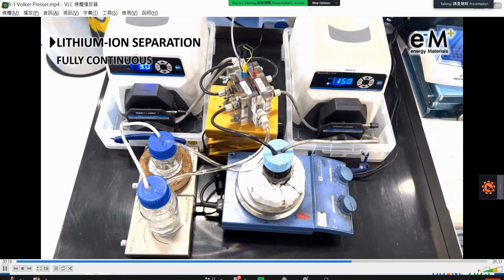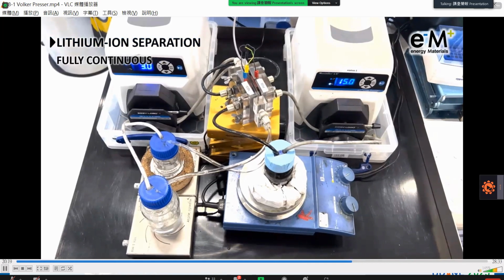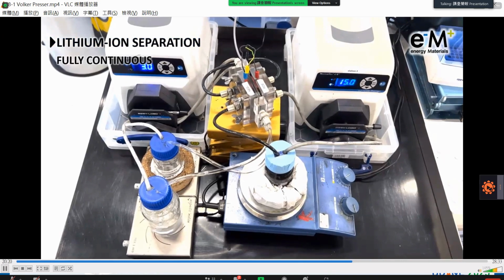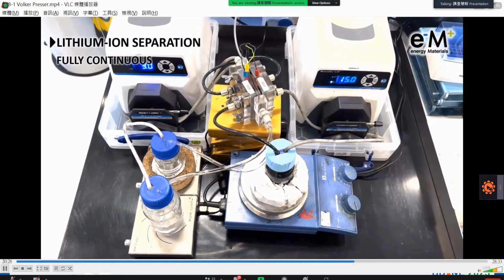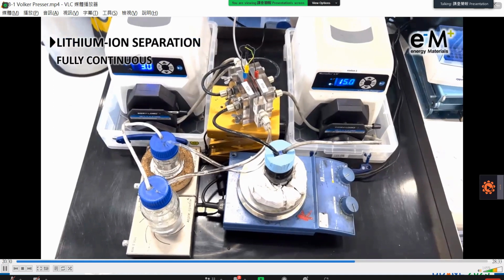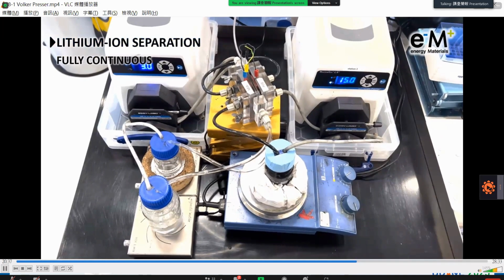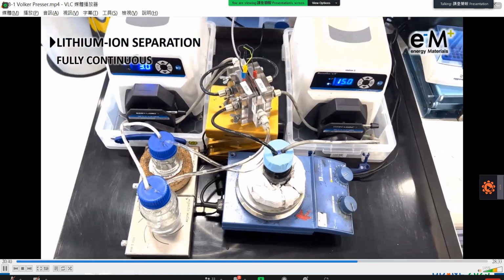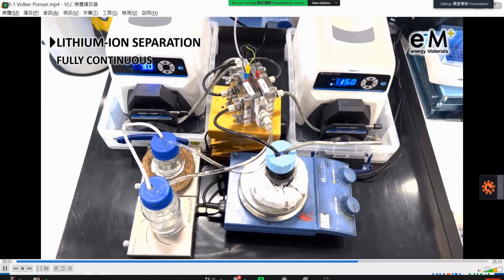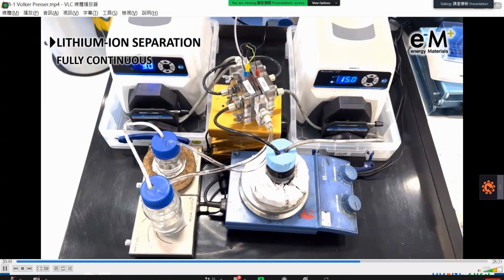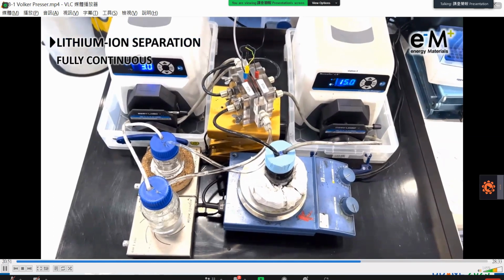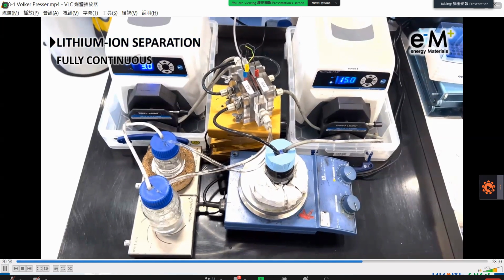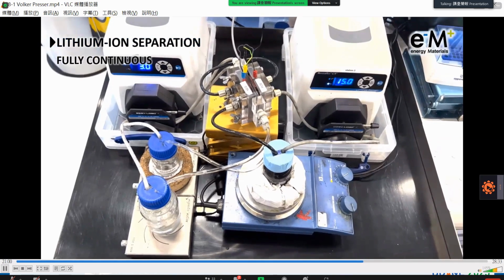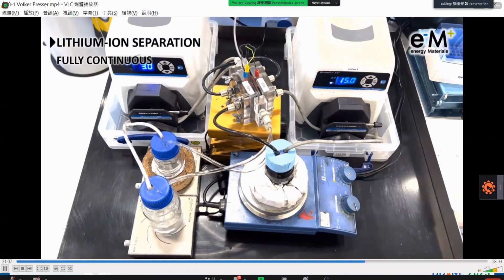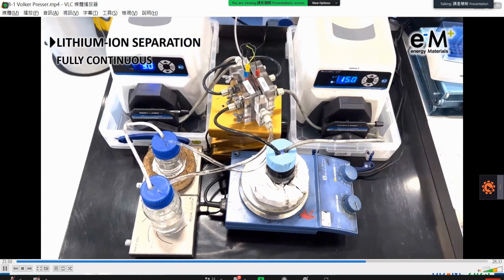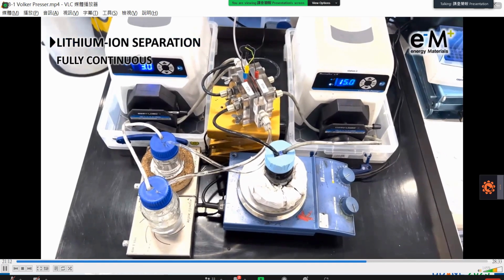However, it is also possible to have the electrochemical lithium extraction combined with a continuous process. Here, in all crudeness of the experimental setup that we explored in our laboratory, you see an electrochemical cell with multiple channels. On one hand, we have the lithium recovery solution that is pumped through the system continuously. We have a feed solution that is also pumped continuously through the setup that contains the lithium initially. We also have in that setup either flow electrodes or, for other setups, a process where we have redox flow battery chemistry circulating, separate side chambers that uptake and release the lithium containing solution in a controlled fashion.